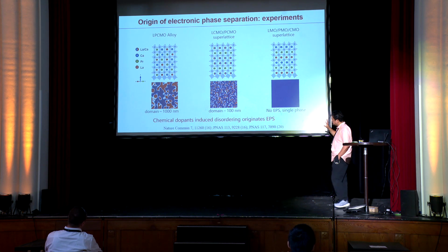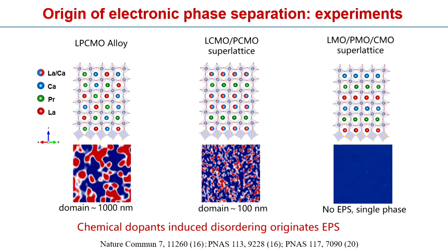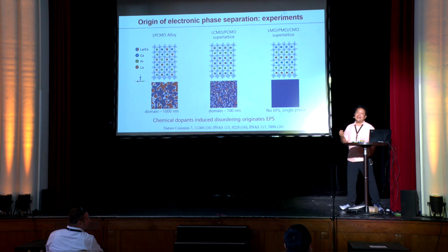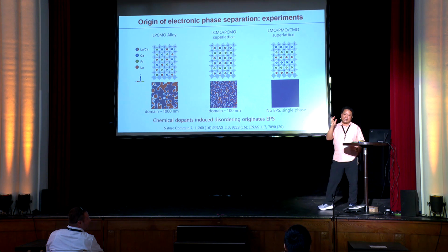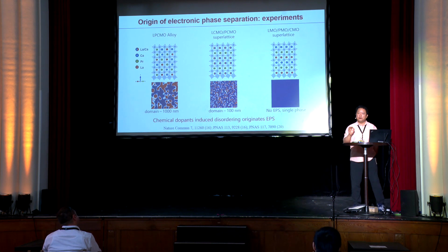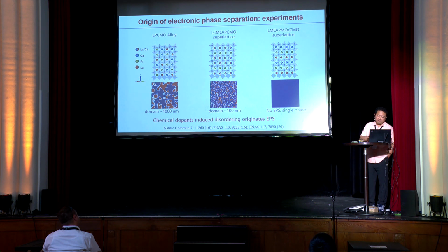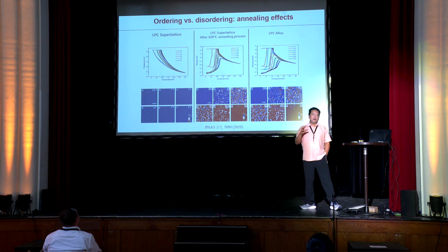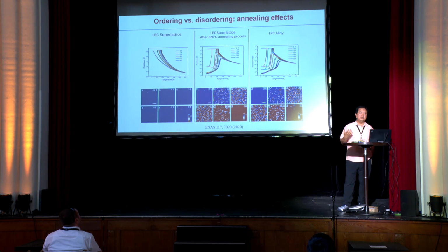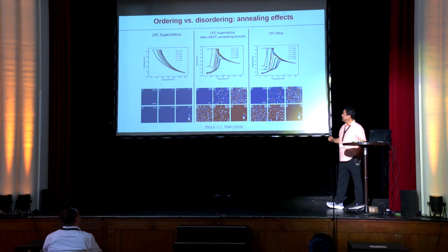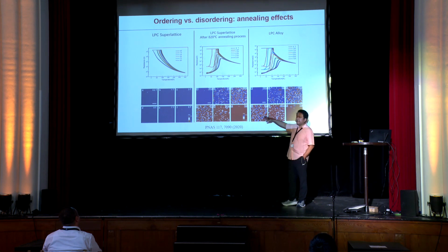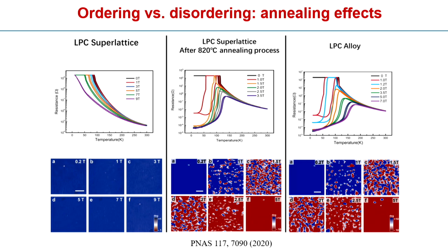So now, at least from an experimental point of view, we can see direct evidence that chemical-dopant-induced disordering is the real physical origin. And this disordering is in fact intrinsic, because there's no way, without doing these very special actions, that you can make these chemical dopants spatially ordered. So this is the reason that any kind of disordering will introduce these electronic phase separations. Even with this perfectly chemically ordered system, if we just do a slight annealing, 20 degrees C above the growth temperature, then you will have some interdiffusion at the interface. Immediately, you recover the electronic phase separation exactly the same as in those LPCMO systems. So this is one way to prove that.